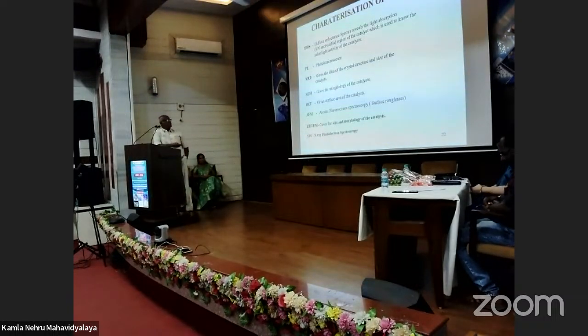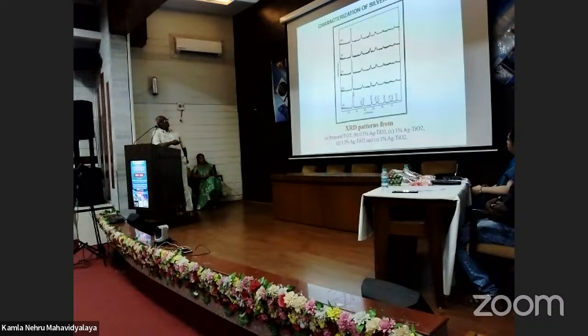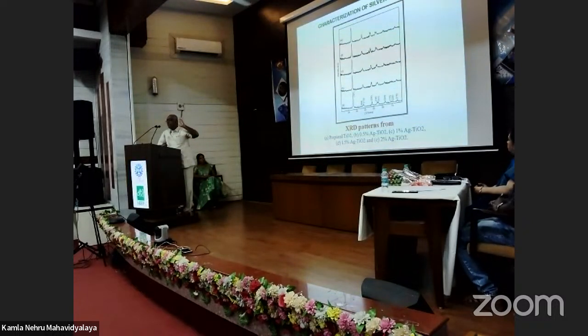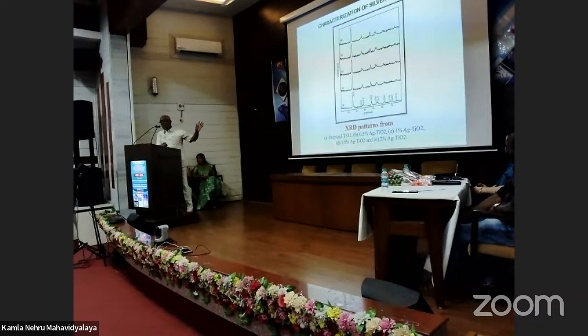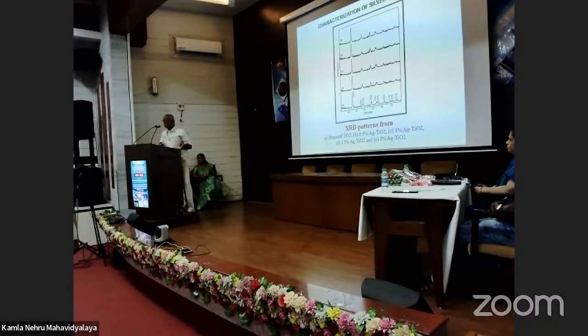So this is generally the method used for characterization of material, and this is the one that we prepared long back, silver doped TiO2. When we reported it, this paper has got more than 600 citations, because at that time we reported silver TiO2 and it was very useful. We tested it only for environmental remediation. Later on, my student, as I told, used it for photocatalytic organic synthesis.